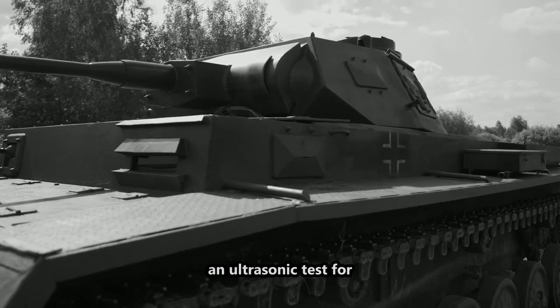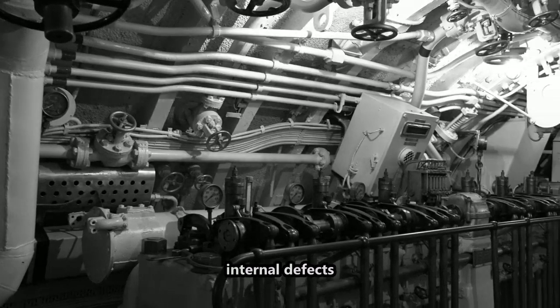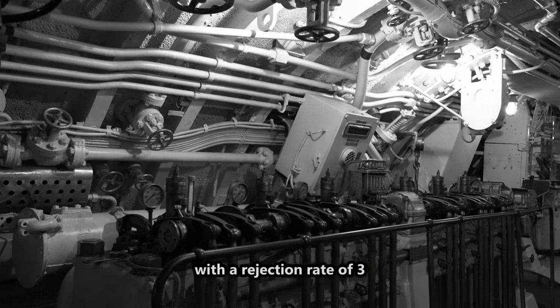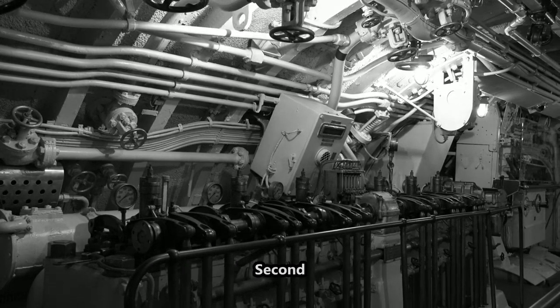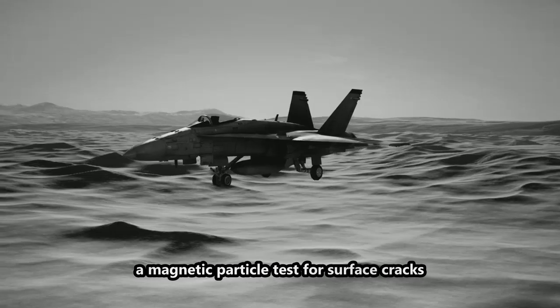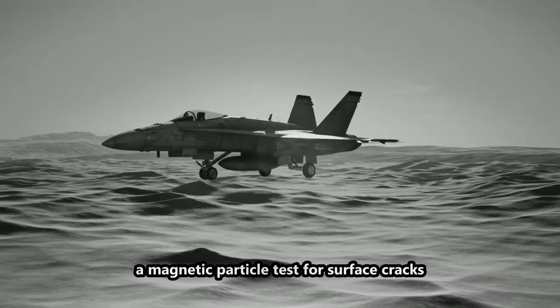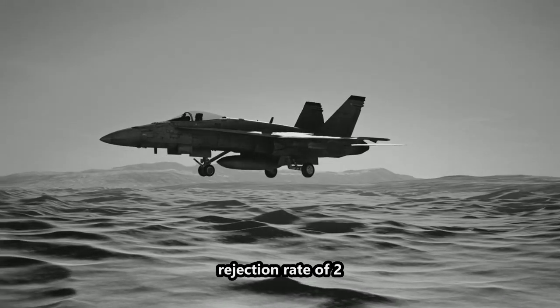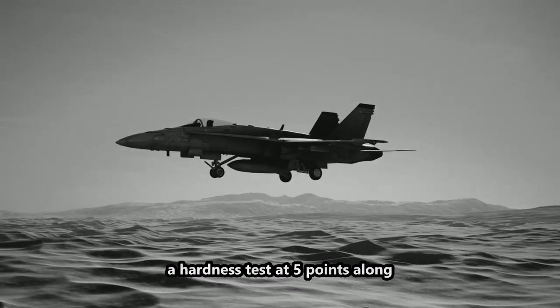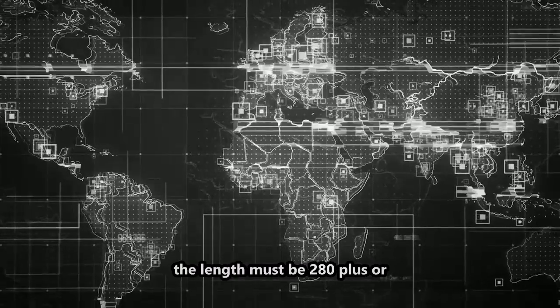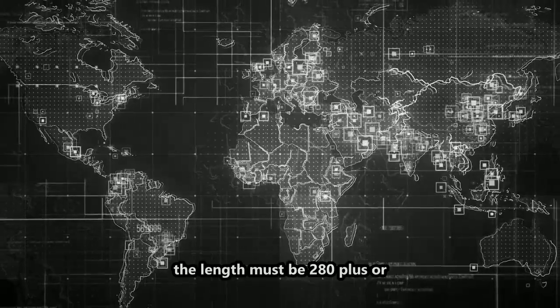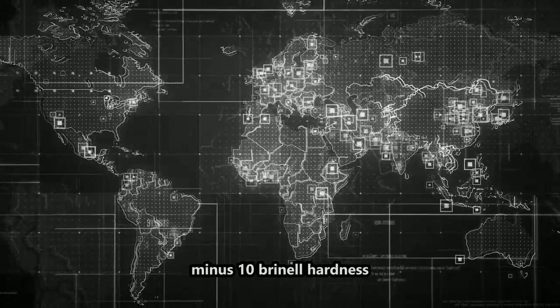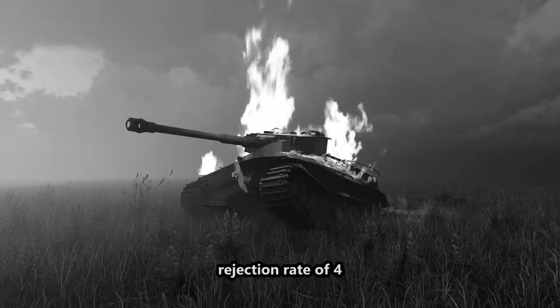The quality control for those torsion bars was equally impressive. Every bar was put through 7 stages of inspection. First inspection, an ultrasonic test for internal defects, with a rejection rate of 3%. Second, a magnetic particle test for surface cracks, rejection rate of 2%. Third, a hardness test at 5 points along the length, must be 280 plus or minus 10 Brinell hardness, rejection rate of 4%.